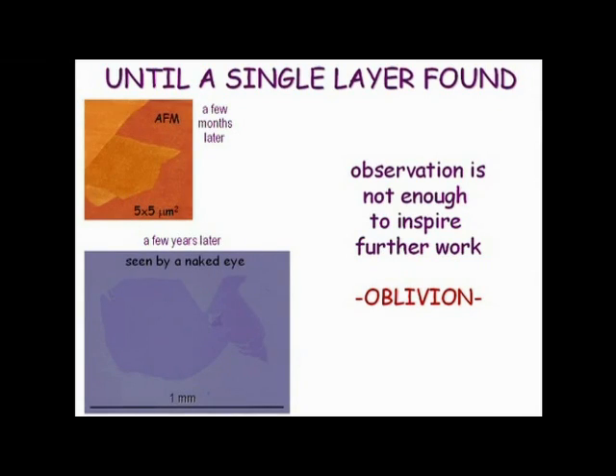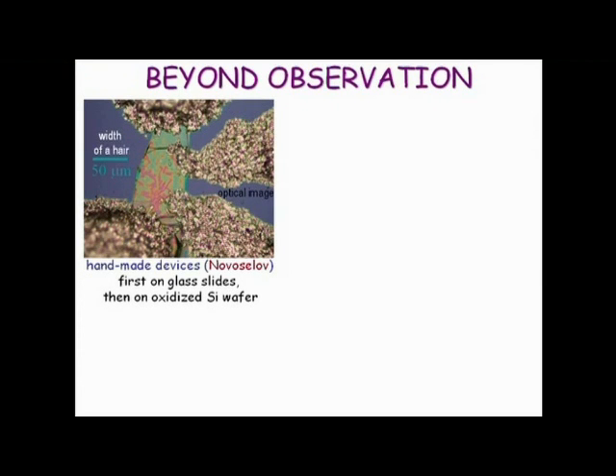So if it would be just observation like it was there, some people say, oh, they isolated graphene, that's great, and this is it. If we left at that moment showing that there are monolayers of graphene, it would be, well, whatever, maybe a publication, and no one would care about this. What was important, we went further. Already at the very first stage, we started picking up flakes of graphite by tweezers and depositing them on glass slides and oxidized silicon, maybe moving in the direction of transistors or metallic electronics.